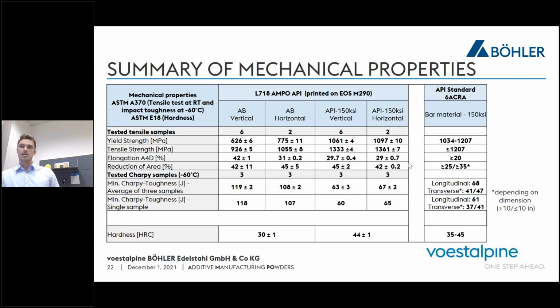So on the one hand side we have really high strength, but also high toughness with 63 to 67 joule for an average of 3 samples. And with the hardness, we are also in the standard with 44 HRC and the standard deviation of 1 HRC.